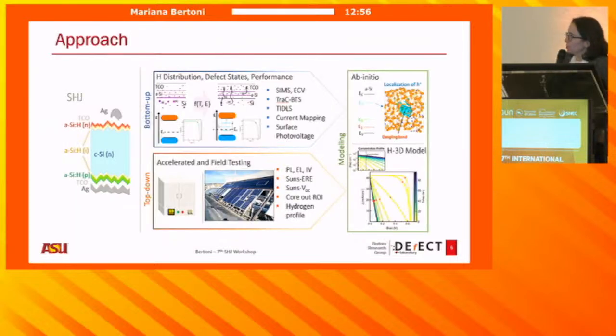The way that we actually tackled this problem was to have a top-down approach and a bottom-up approach. So we built different layers. We built the heterojunctions up. We started with a good quality silicon, we put intrinsic amorphous silicon, doped amorphous silicon, we did symmetric structures, and then we did SIMS, ECV, we threw the kitchen sink at these interfaces. The other thing that we also did is, using the same or very similar silicon quality, we fielded several modules, and we also looked at some modules that have been in the field for quite some time. And hopefully, we put some modeling people to work, some molecular dynamics, some ab initio calculations, and we could bridge the top-down approach and the bottom-up approach.